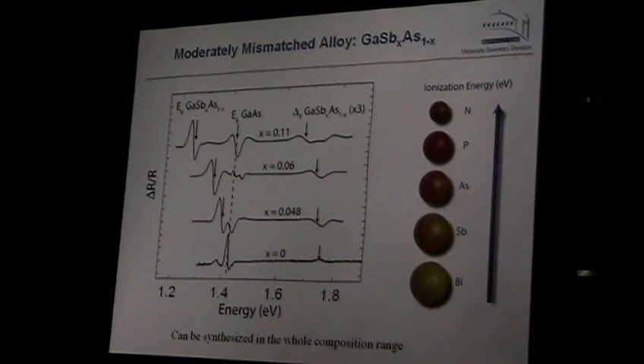So now, also, of course, there's a whole range of potential materials. We start with the very well-matched material, gallium arsenide phosphide. We go to very highly mismatched material, gallium arsenide nitride. However, on the way, we can have materials like gallium antimonide arsenide. These materials are much friendlier in the sense that it's easy to synthesize them, and you can study very interesting properties of how this band anti-crossing affects properties of the material, because these materials can be well synthesized.